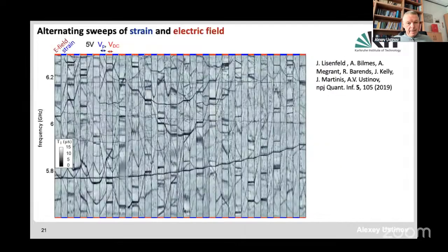So the result of the measurements where we were applying alternating sweeps of strain and electric field is shown here. On the horizontal bar above, you see the red regions where we were changing only the electric field, and then blue regions where we were changing the strain, and then electric field again, and strain again, and so forth. And then, as you see, some of the defects react only to strain, like, for example, this defect, changing its frequency very rapidly, and then staying constant in frequency under the effect of the external field.